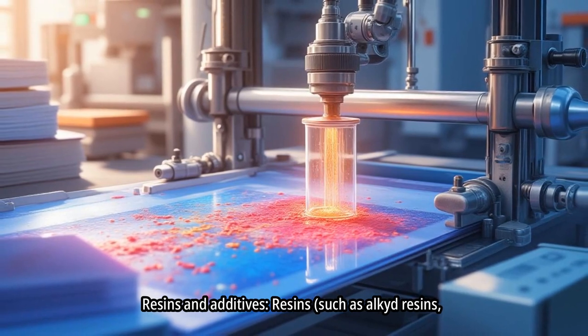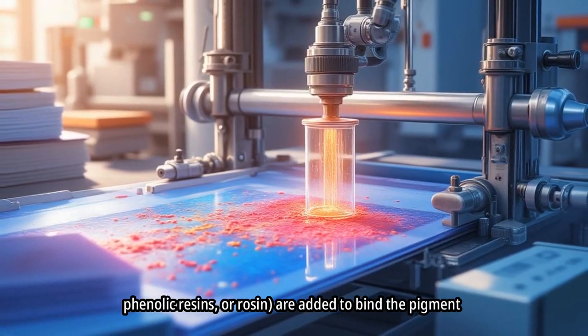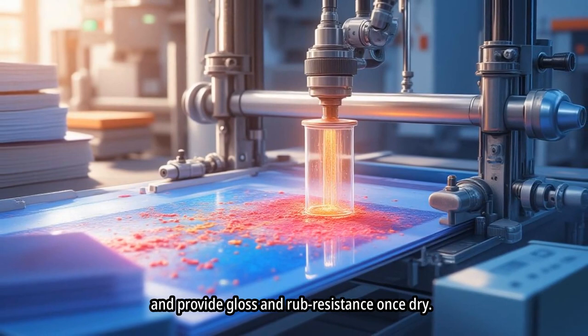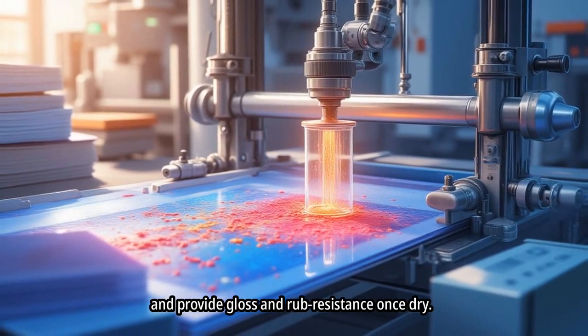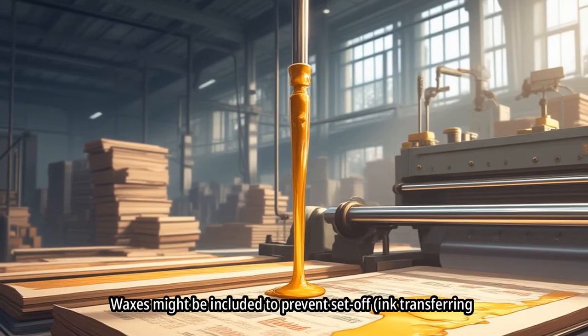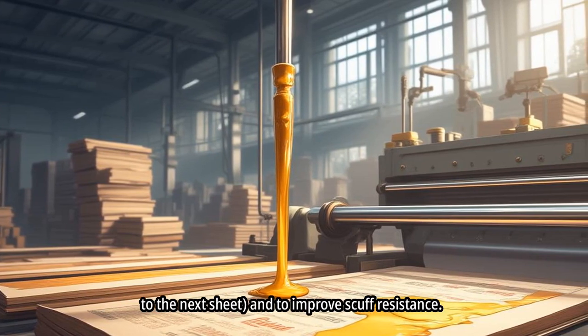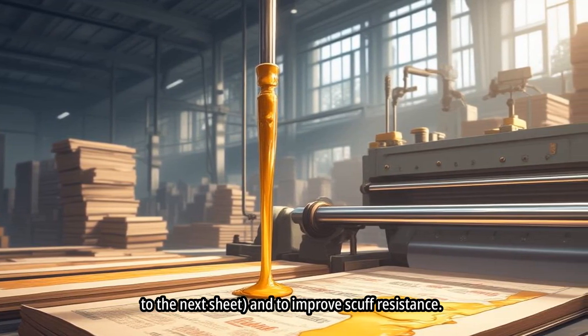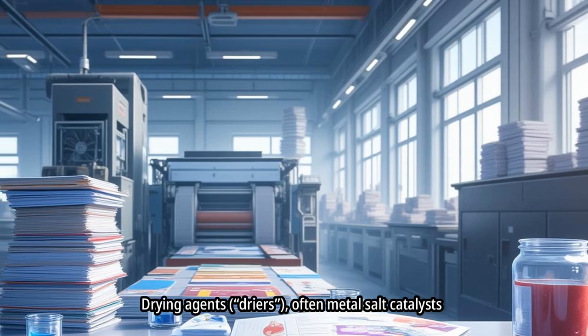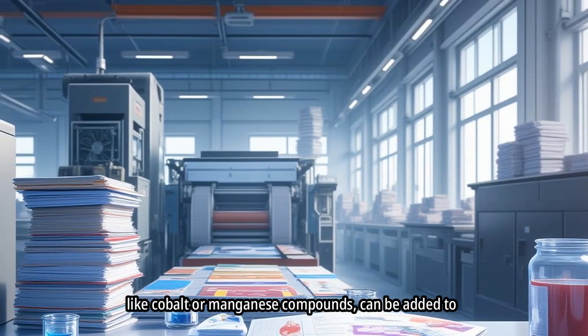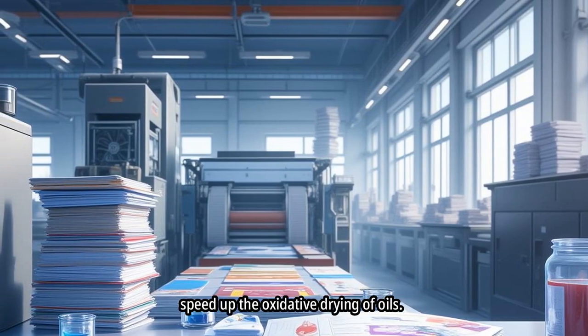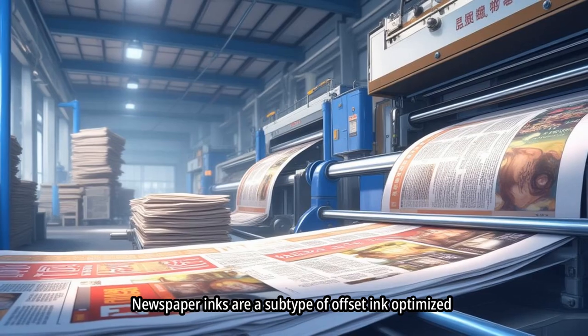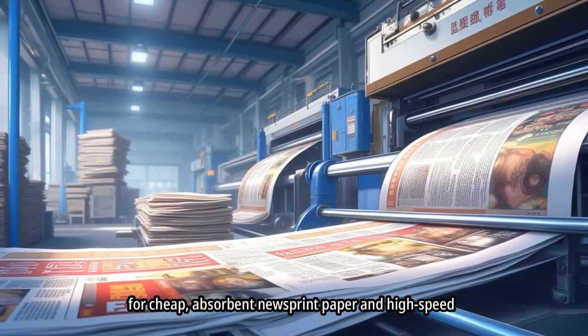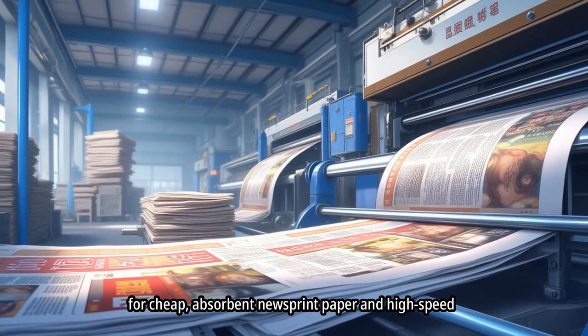Resins, such as alkyd resins, phenolic resins, or rosin, are added to bind the pigment and provide gloss and rub resistance once dry. Waxes might be included to prevent set-off, ink transferring to the next sheet, and to improve scuff resistance. Drying agents, dryers, often metal salt catalysts like cobalt or manganese compounds, can be added to speed up the oxidative drying of oils.